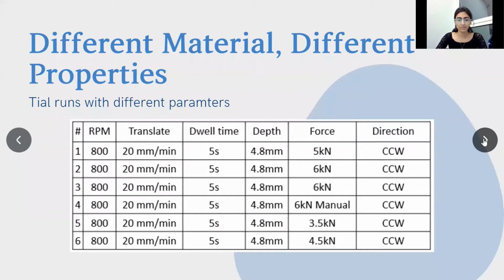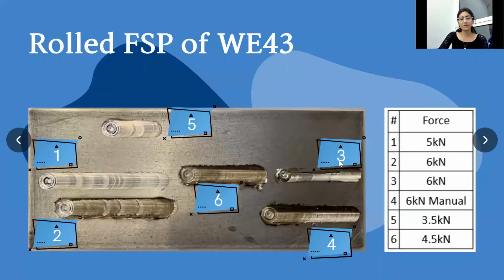Different properties, different materials. Just as we cannot heat everything up to 1000 degrees Celsius because aluminum will melt way quicker than steel, we need to find the amount of heat that we need to generate to achieve a perfect weld. To do that, for the magnesium alloy WE43, we did trial runs with different parameters. We managed to find the best possible parameters in terms of RPM, translation, dwell time, and depth.